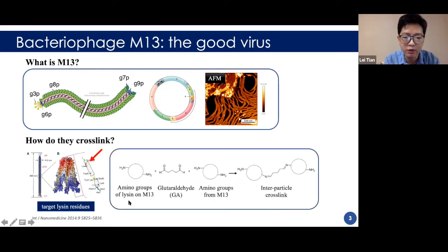You can see the equation of the cross-linking reaction here. Glutaraldehyde is an aggressive carbonyl reagent that condenses amines via Schiff base formation. It was commonly used to prepare antibody-enzyme conjugates. Glutaraldehyde reacts with lysine residues on the phage coat protein. They can react at room temperature and near neutral pH.